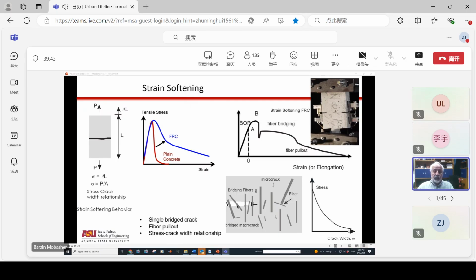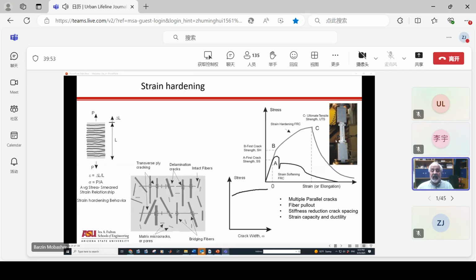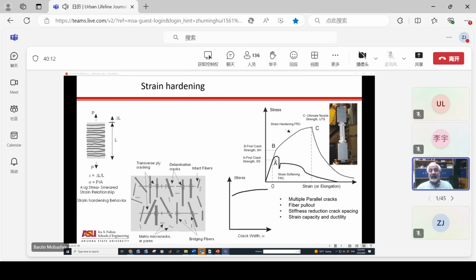And that can be represented by a stress crack width relationship or crack width projection and all of the parameters that I talked about before. But this basically puts us in a domain of strain softening. If I go with a higher amount like textiles or UHPC or such, now there is so much fiber in here that as soon as one crack forms, then there is more energy available for growth of a second crack and third crack or so. So I get these parallel microcrack systems. And that would mean that I go into a strain hardening response before I get into this softening.